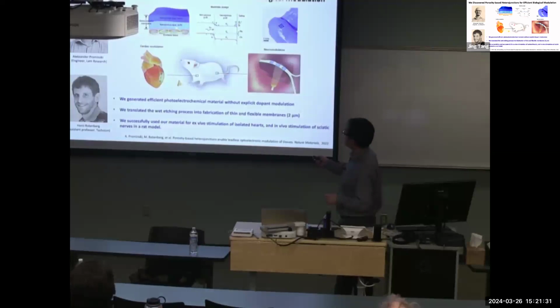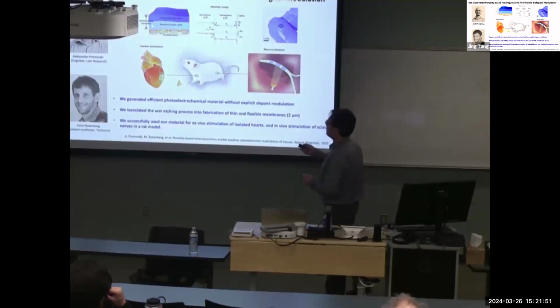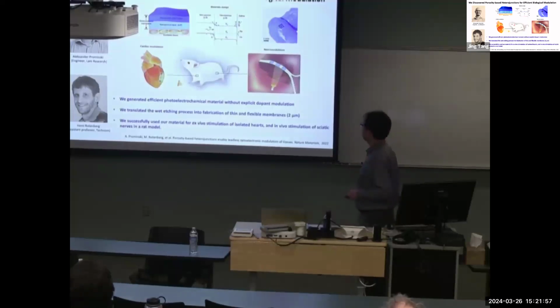The conclusion is that we discovered by accident a heterojunction we call a porosity-based heterojunction. It contains two layers. One layer is non-porous; essentially, it's the commercially available silicon wafer. And another layer is a nanoporous layer. It can be 1 micron to 5 micrometers thick with a pore size on the order of a few nanometers. How can we generate the nanoporous layer? By etching, which is also a decades-old method, but we found this by accident.